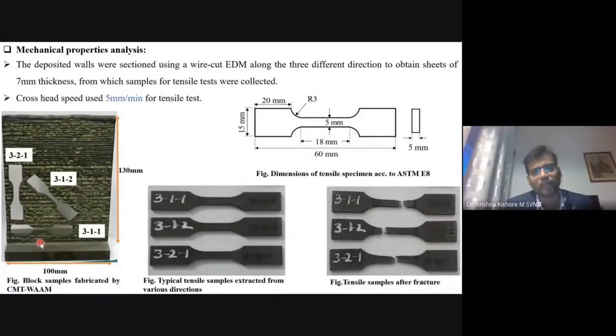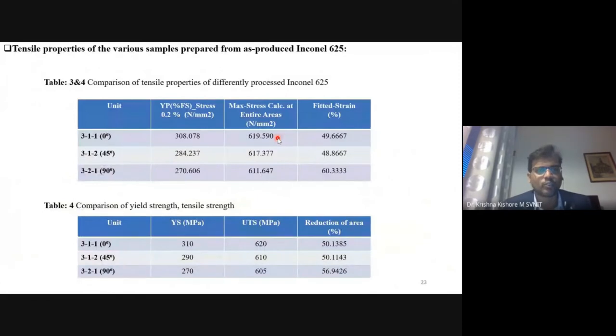And in the case of WAAM, as I said, there are anisotropic properties, so to evaluate these anisotropic properties, people extract samples at 0 degree, 45 degree and 90 degree, right? These samples are taken as per ASTM standards, and are tested with respect to tensile properties and microstructure. We have characterized these and studied the mechanical and microstructure properties. So these are some of the properties shown for the 0 degree, 45 degree and 90 degree, and you might see that in the case of 0 degree samples, the yield strength or the maximum UTS is quite high compared to the other cases.